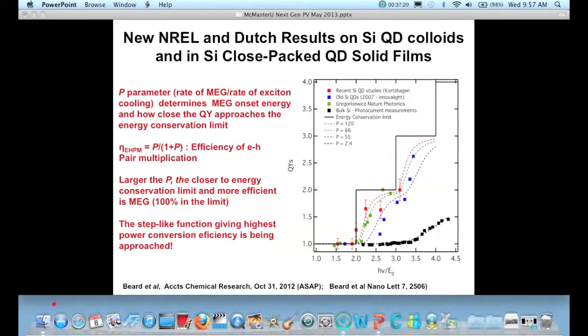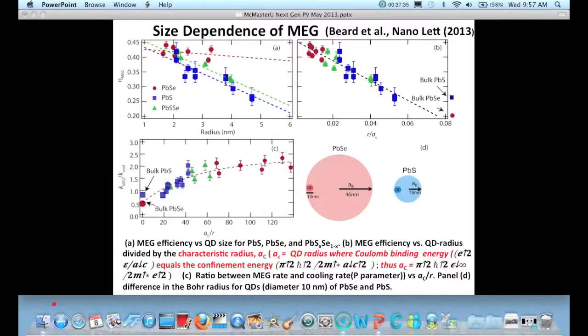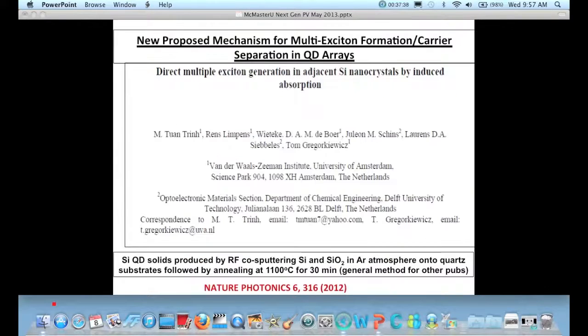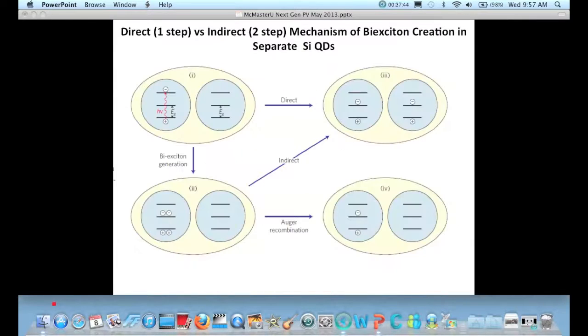I'll skip this, but this is an interesting result published by a group in Holland, that when you make silicon quantum dots in a silica matrix, an amorphous matrix, you also get very efficient MEG that has an onset of 2. And what's very interesting in that result, which is this paper here in Nature Photonics of last year, is that they say they see the appearance of the 2 excitons immediately in 2 separate dots.